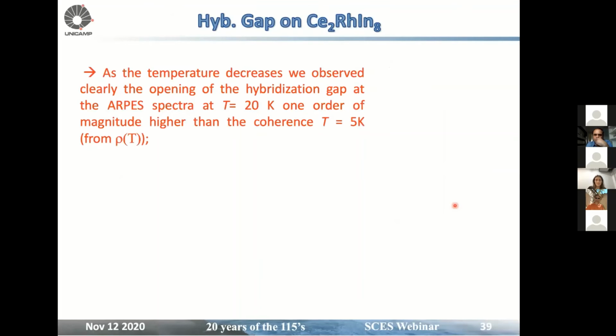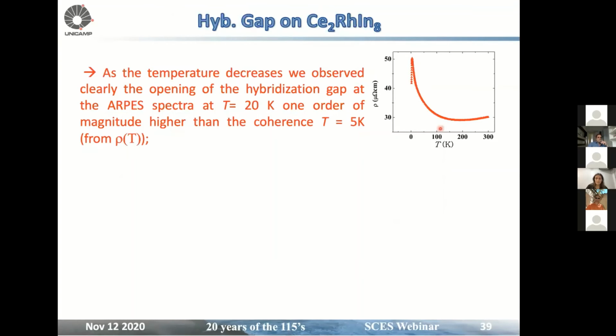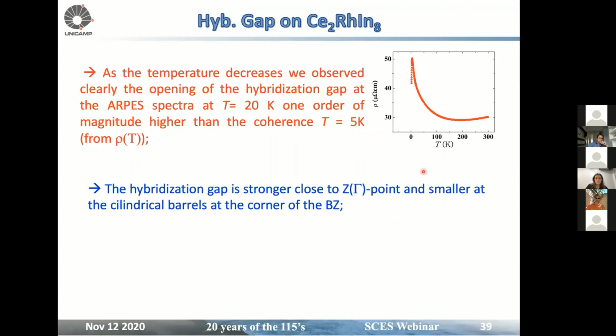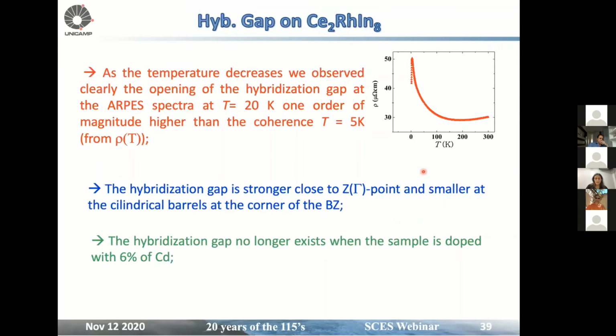So, concluding on the hybridization gap in Ce2RhIn8. What is nice is that as temperature decreases, we clearly see the opening of the hybridization gap in ARPES at around 20 K. That is one order of magnitude higher than the coherence peak of the resistivity curve. So the hybridization is strong at around the Z point and no longer exists when we dope with cadmium.